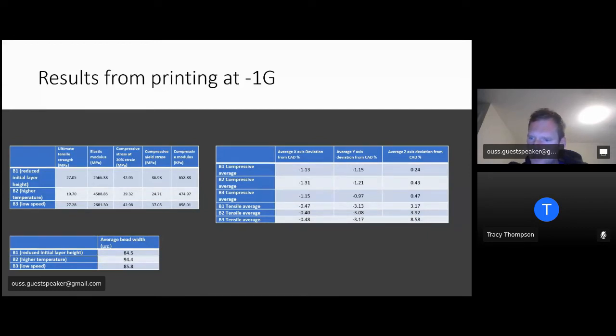Deviation with CAD is on the right there. That's the distance between the edges of the parts being manufactured compared to CAD, and the average bead width is down there on the bottom left. That's how wide the extruded bead is. And as you can see, there's a big difference there for higher temperature, and that's probably because of the change in viscosity. That's really important for spaceflight, because as all you space engineers know, temperature varies widely for space applications. So that is showing that changes in temperature are very important, and I'll explain why later in this presentation.